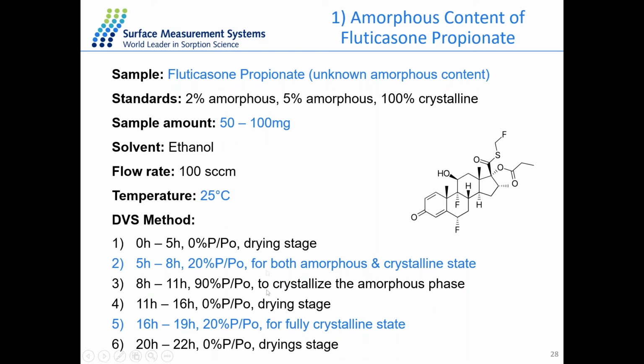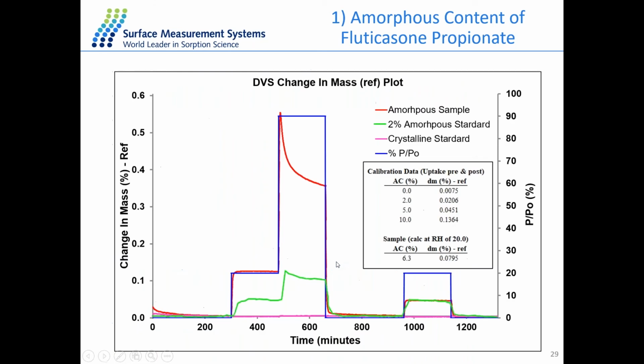So it first begins with a drying stage, and in the middle there are 2 important stages: 20% RH before the crystallization point, and we compare the mass change of the material between the 2 20% RH steps. So here's the result for the experiment. The red line is the sample of interest, the amorphous sample with unknown amorphous content, and the green line and the pink line are the standard materials, fully crystalline material, and then the 2% amorphous content material as the standard.